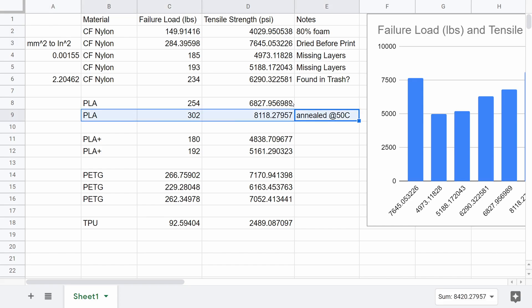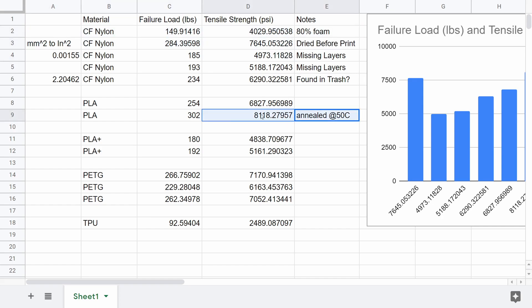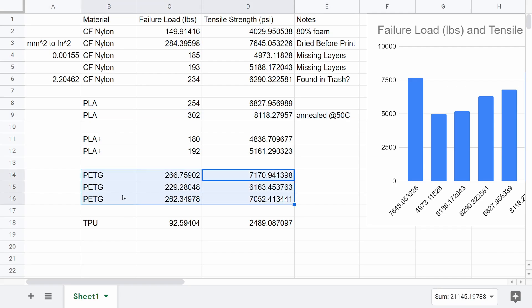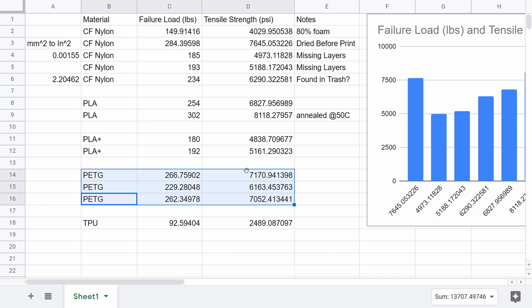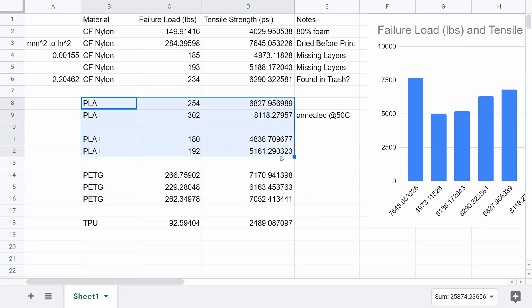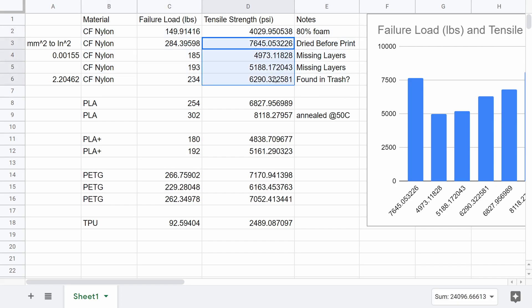I'm not sure what the deal was with this one that I found in the trash. That might have been the third sample from my print that was missing some layers. So I can't really say whether that was the annealed sample or the missing layer one. And if we look at the one sample that I know I dried before printing and did not anneal, it actually ended up performing second best out of all the materials, second only to this PLA sample that was annealed. This isn't the best data because I was kind of losing track of specimens and stuff, but what we can see here is that the carbon fiber nylon print was actually very strong, and PLA was also very strong.